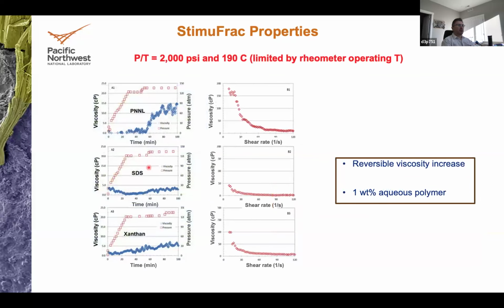The viscosity, so we compare the viscosity, and unfortunately the rheometer can only go up to 190 Celsius. So we see some changes in viscosity, not as high as I would expect at higher temperatures, but nevertheless, this is time, this is viscosity values, and this is pressure. As you start increasing the pressure of CO2 at 190 Celsius, you have a little bit of vapor pressure from the water, and then as you increase the pressure of CO2, about 120 atmospheres, which is about 1600, 1700 psi, you will see that the polymer solution starts reacting with CO2 and increases viscosity. We then depressurize and the viscosity goes down to near water.